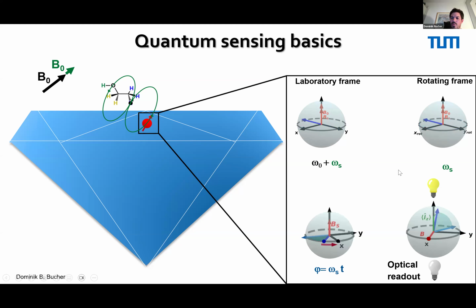Okay, and again, you see that we get this what we call phase accumulation, which gives information about the coupling. Here it's basically omega t, that's how far the spin vector of the NV center has moved. And then we do some more rotations on the Bloch sphere so that at the end we can read out this quantum state again by the spin-dependent fluorescence. This is, again, a very simplified picture of how the sensing works.